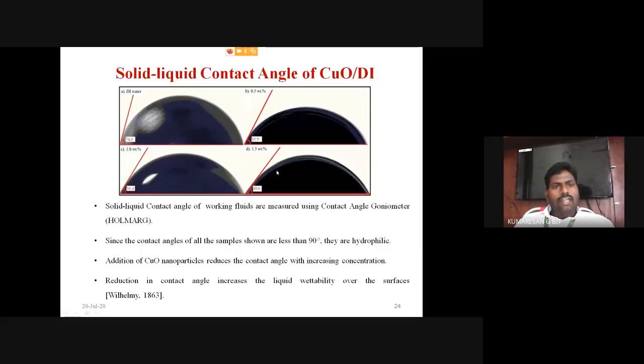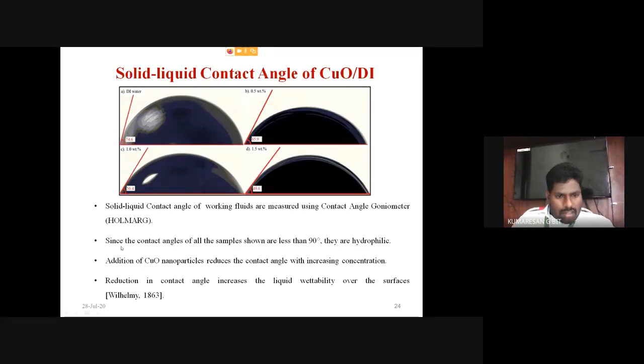The next one is the solid liquid contact angle. This is having a relationship with the surface tension. Then if surface tension increases, that capillary force increases. Then the solid liquid contact angle of working fluids is measured using a contact angle goniometer. Since the contact angles of all the samples shown are less than 90 degrees, this means all are hydrophilic in nature.